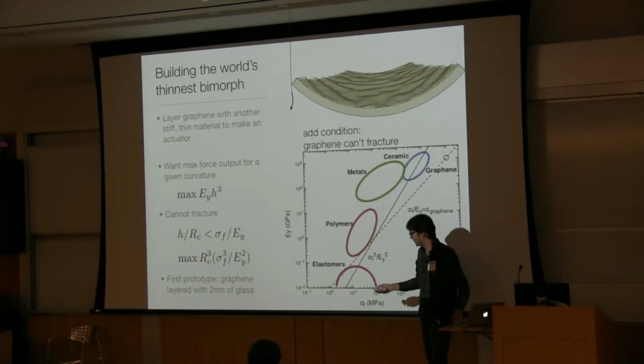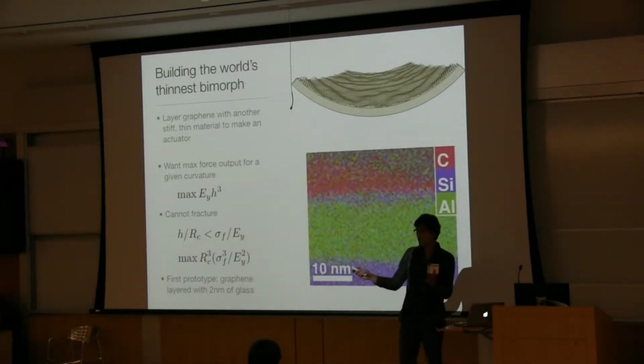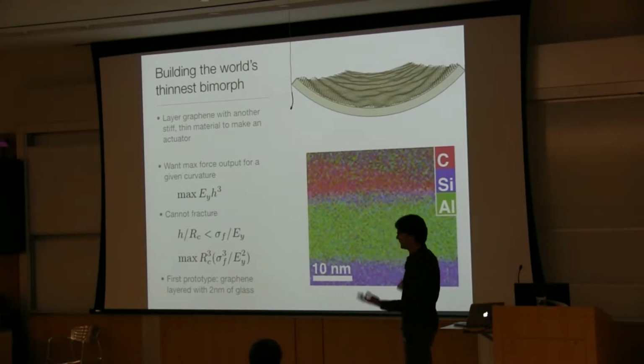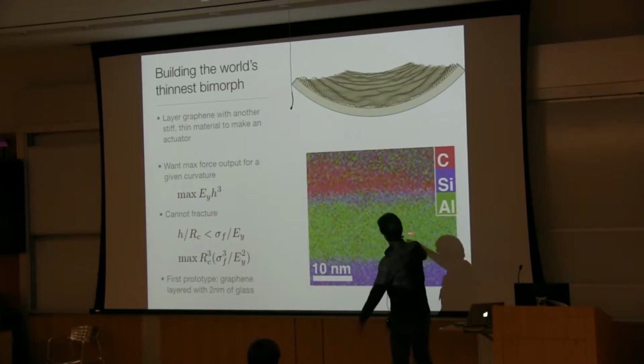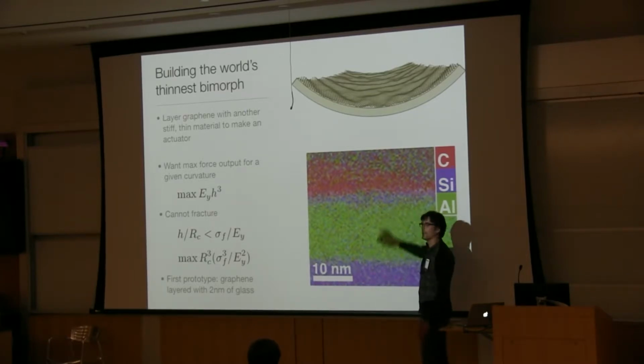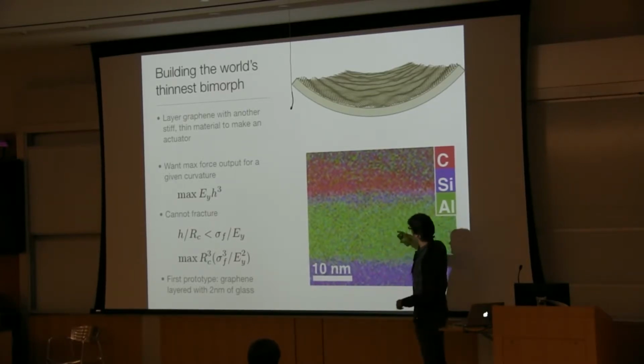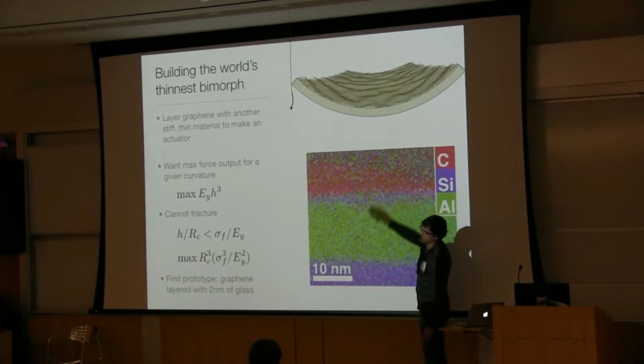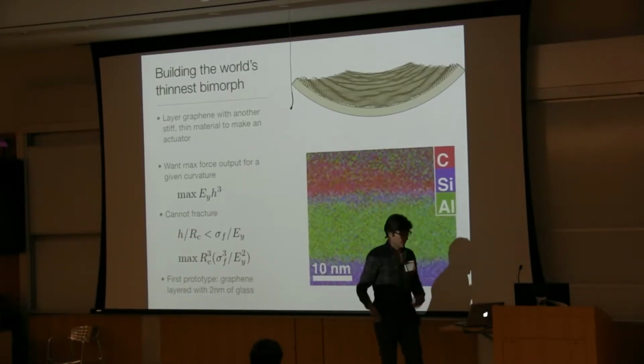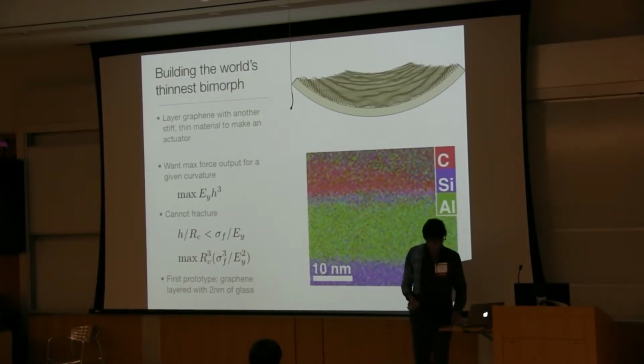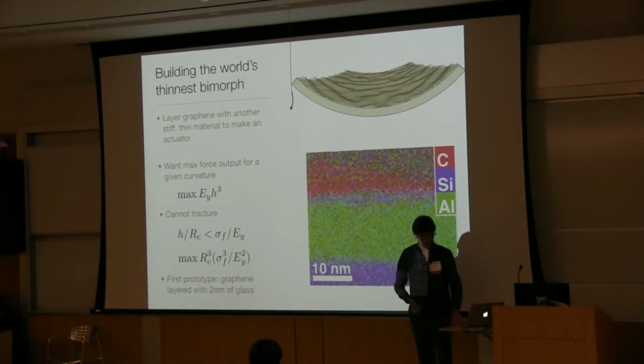We made graphene layered with 2 nanometers of glass. Here it is, this beautiful cross-sectional TEM that David's group helped us with. What you see here is a layer of aluminum. This is aluminum oxide. It's a release layer. We etch it out with hydrochloric acid to release our devices. Here's this 2 nanometer thick layer of silicon dioxide that we grew. And on top of that, this is graphitic carbon sitting on top. That's the graphene layer capping off our little actuator. So, okay, this is what we're working with in cross-section.